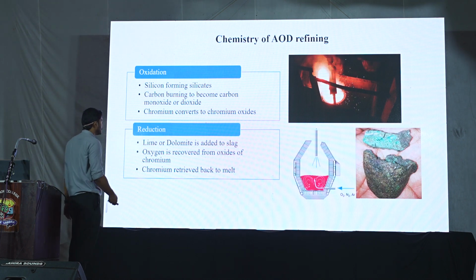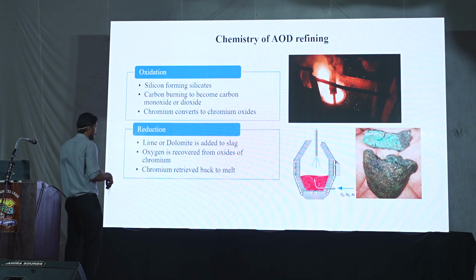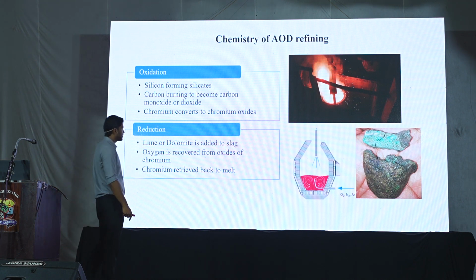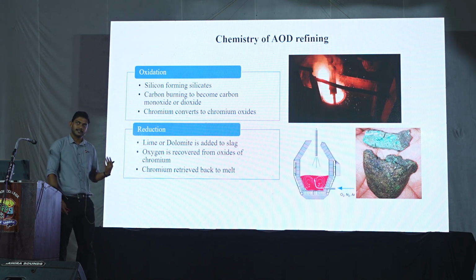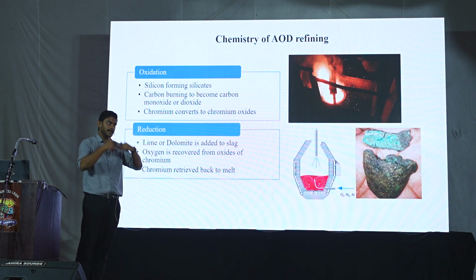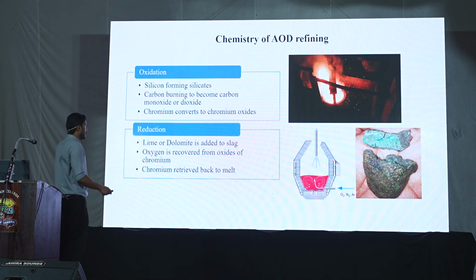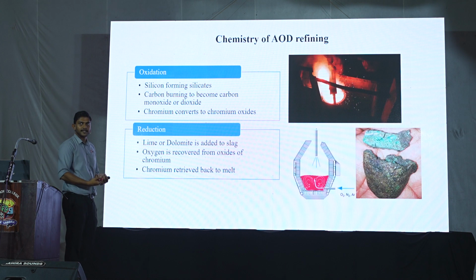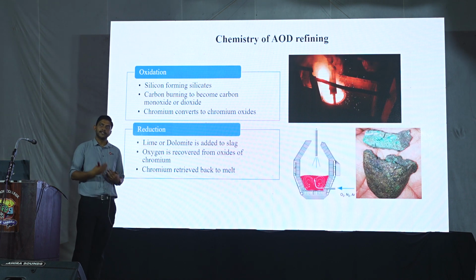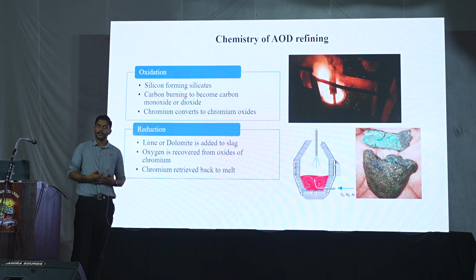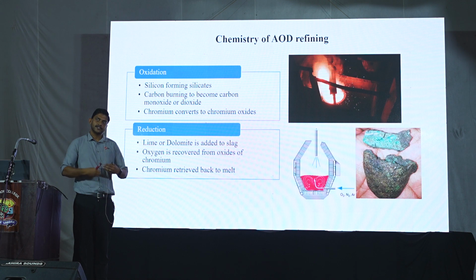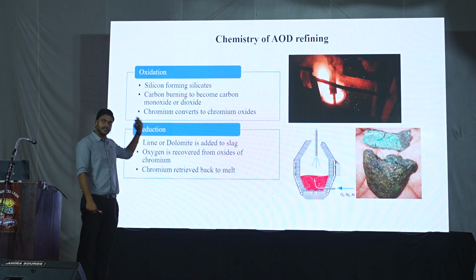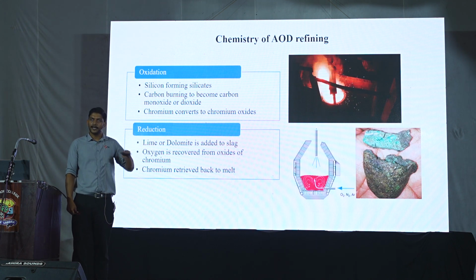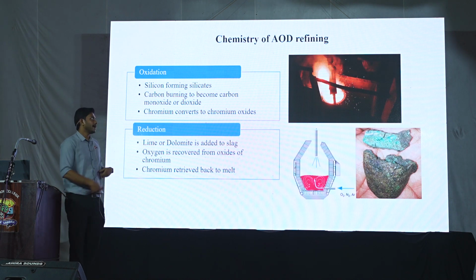After that, what we do, we add lime and stop the supply of oxygen, only argon goes in, stirs, chromium kind of comes back into the molten metal, and due to argon stirring, it gets mixed up uniformly. And with this, most of the impurities, we consider aluminum as an impurity also because it affects some kind of properties. So all such elements which can be oxidized go out, and the material is comparatively clean. We get the chromium back, and we pour it.